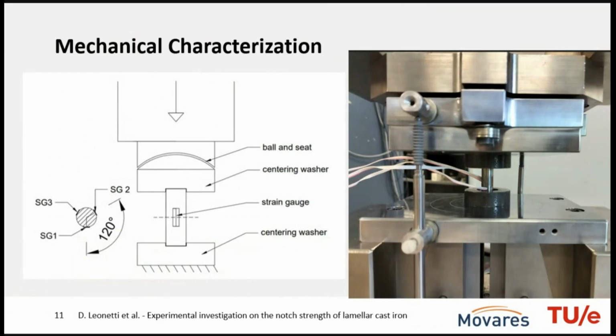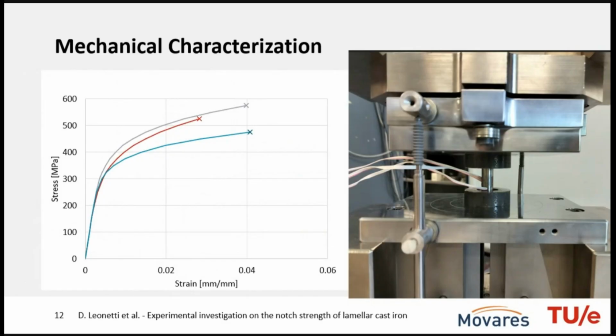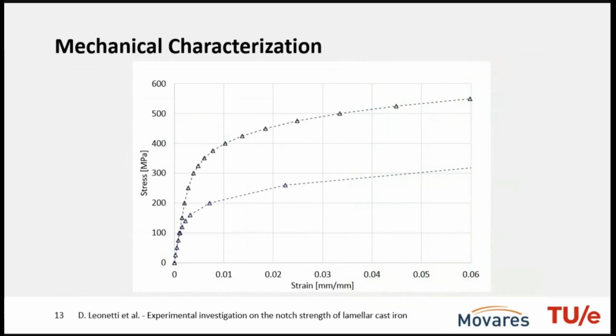Then we also performed compressive tests on cylindrical specimens. We also used strain gauges to quantify the strain. And you can see here the very high performance of the material in compression. Bringing these two curves together, we also quantified the Ramberg-Osgood parameters.